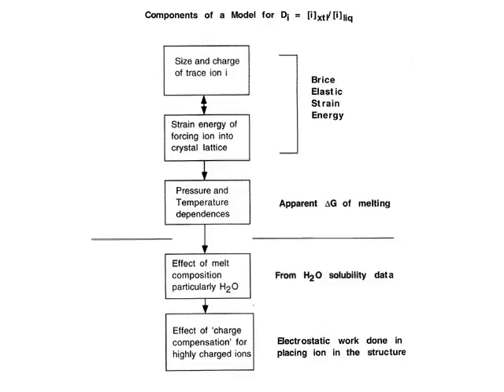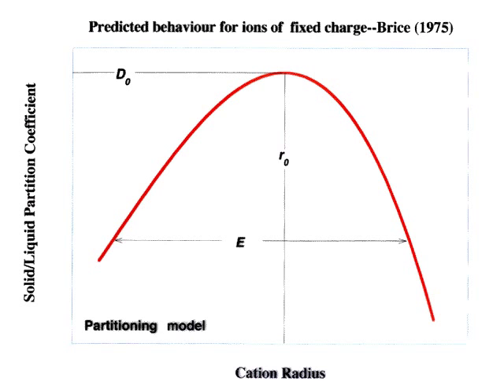This has appeared numerous times in the literature, and the simplest model is that of Brice. If you take plagioclase and look at partitioning of 2+, 1+, and 3+ ions between plagioclase and liquid, you find that they do indeed obey this parabolic relationship. The nice thing about this simple theory is that we could use sodium partitioning to predict cesium partitioning, or calcium partitioning to predict barium or even radium partitioning — which is something no one in his right mind would want to measure.